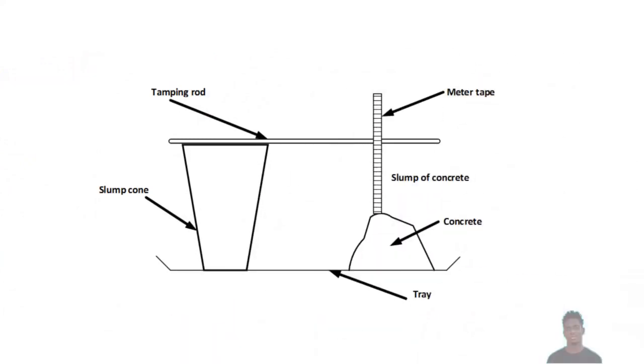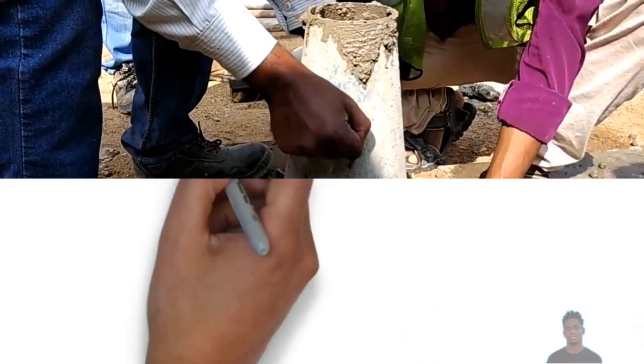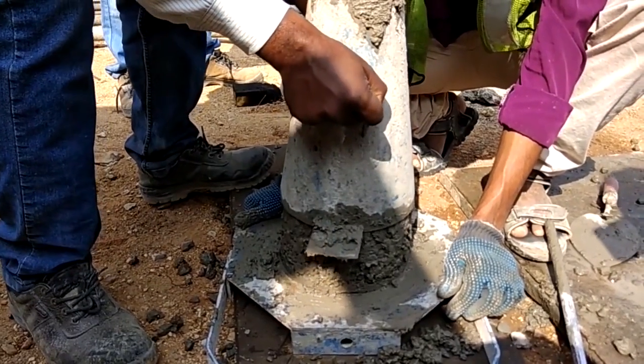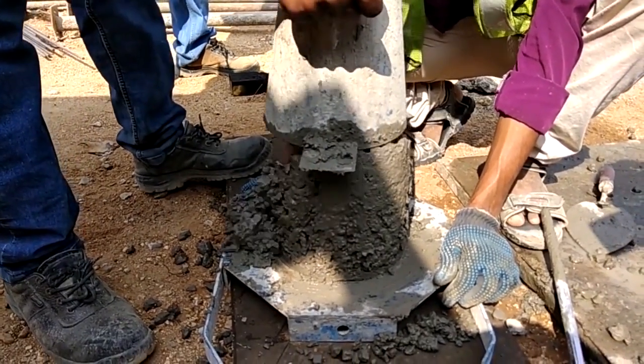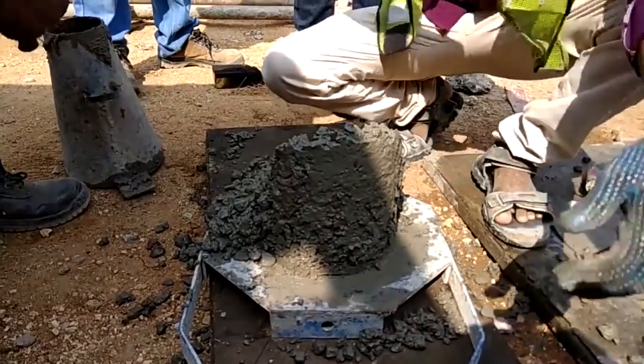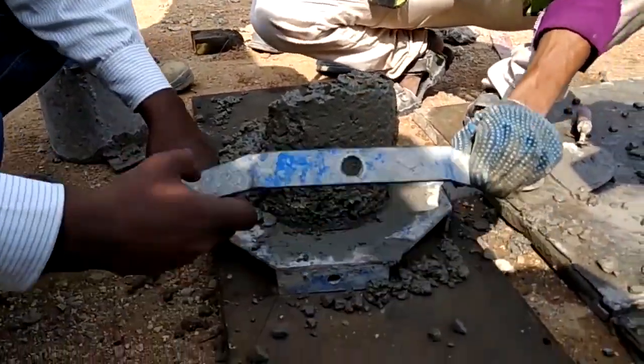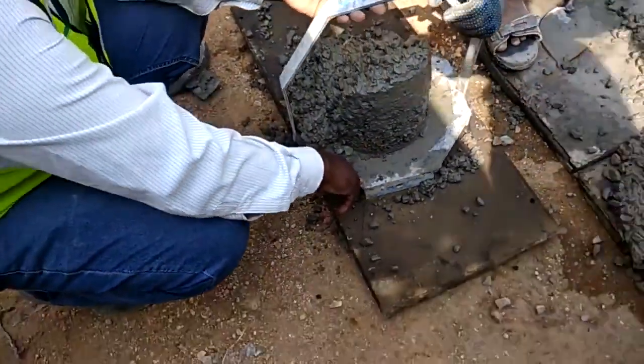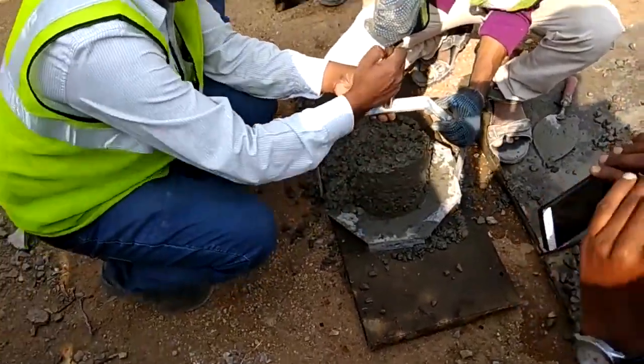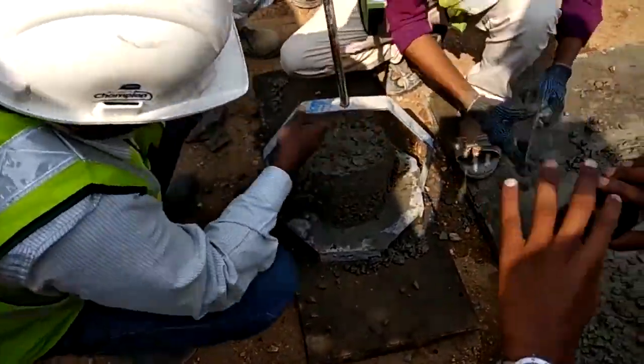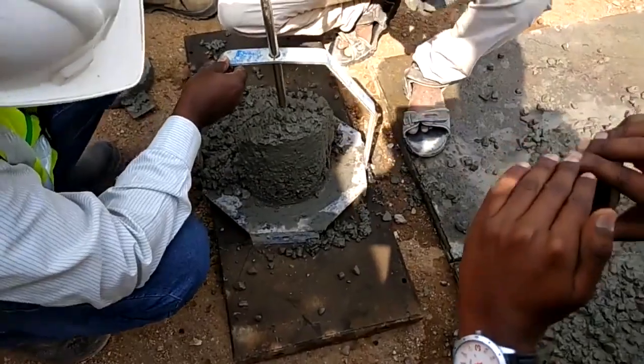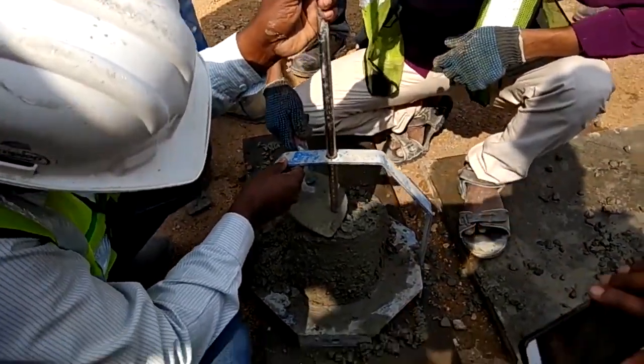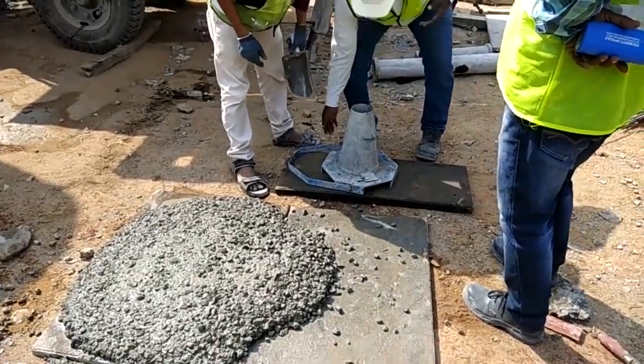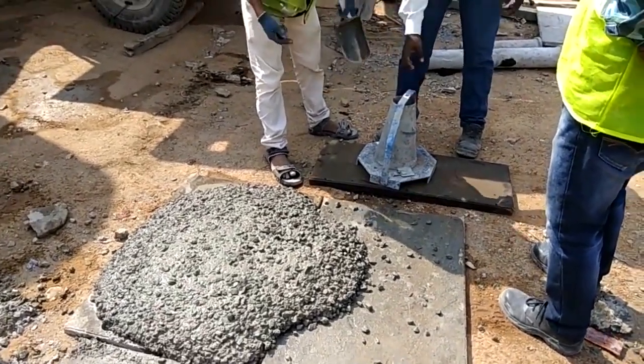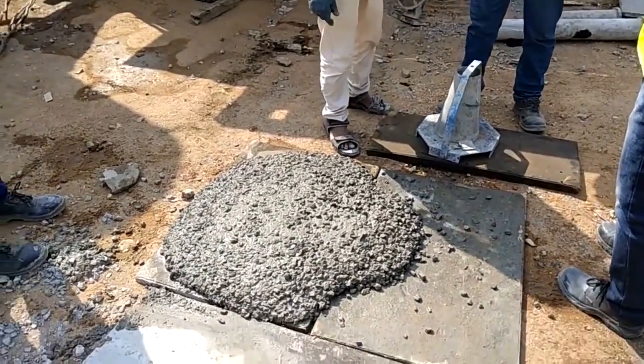The concrete slump is determined by calculating the difference between the height of the mold and that of the highest point of the specimen. Now, if the concrete mix is too wet, then the concrete will slump down on one side, and when this happens, you will need to remix the concrete. This is because concrete is weaker and more prone to cracking when the mix is too wet. If it is too dry, then there will be no slump at all, and when this happens, you may need to add more water to the mix.